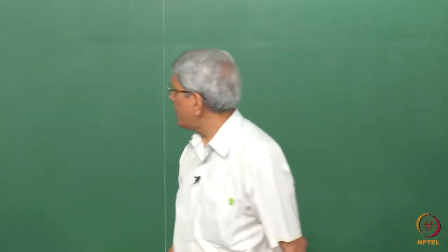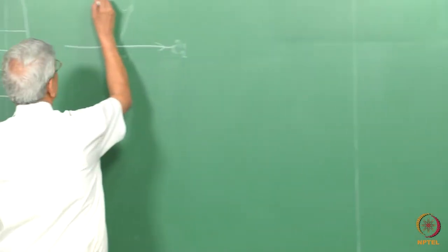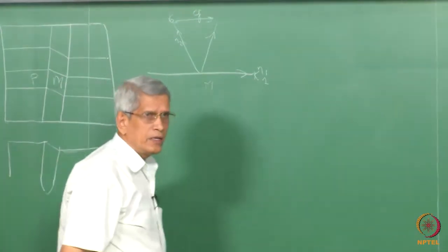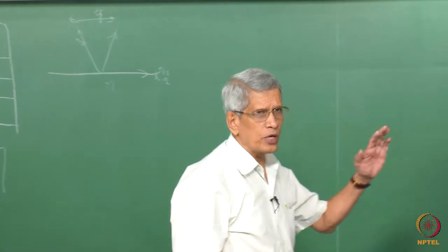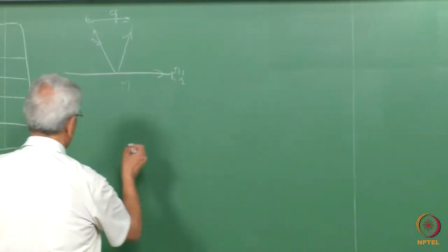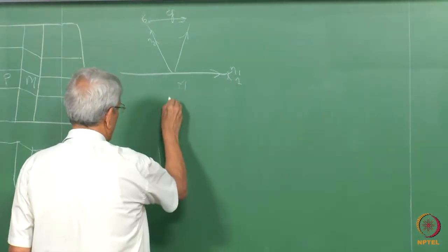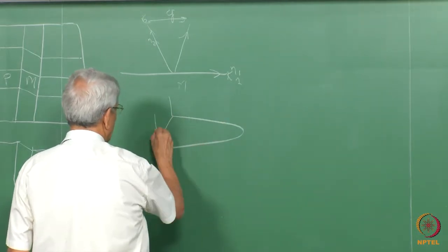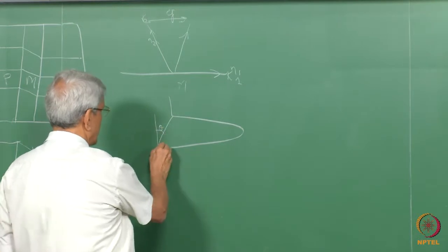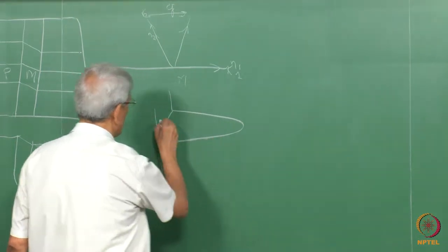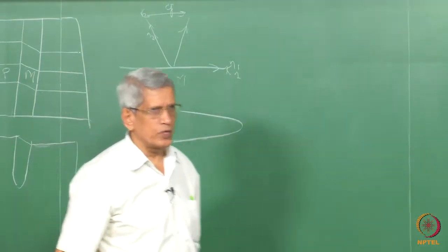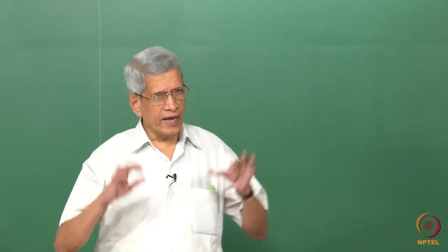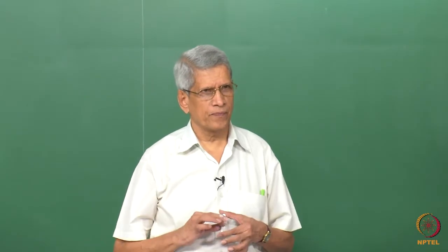Correct. And the simple shear essentially is that from here to here some twinning shear G has been given. This could be easily observed by looking at the surface of the sample. This is how the twin matrix looks. So if you measure this angle, if this is the composition plane, then we can find out the twinning shear, or the simple homogeneous shear which we are applying.